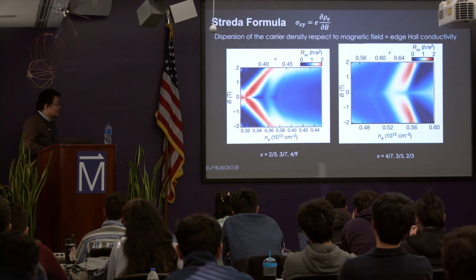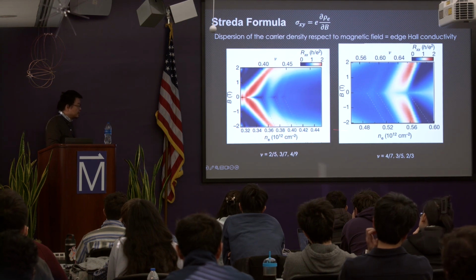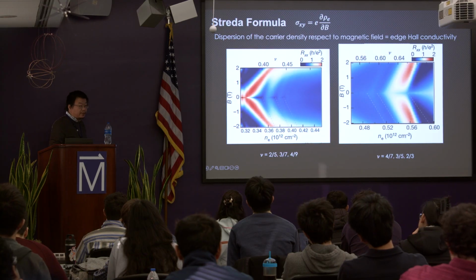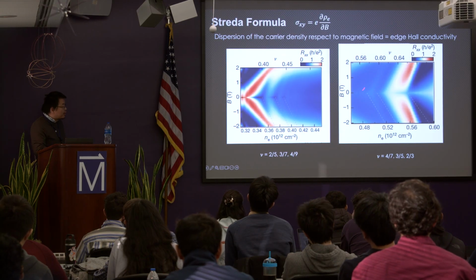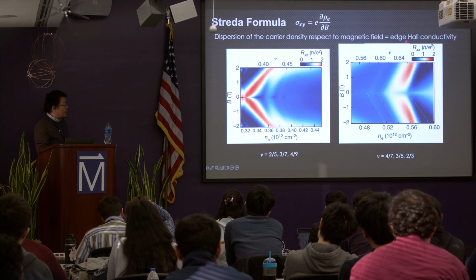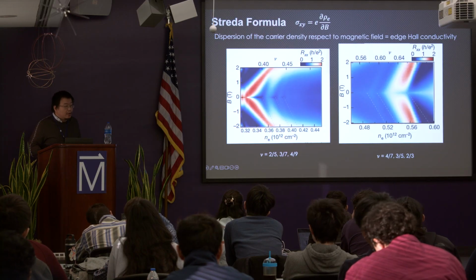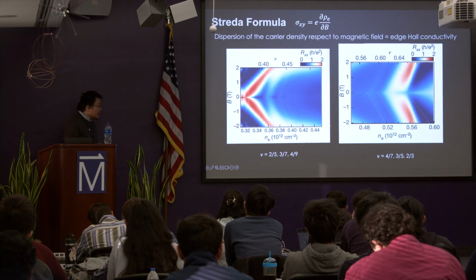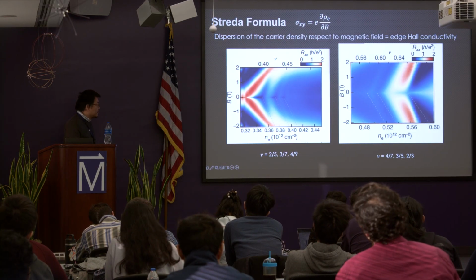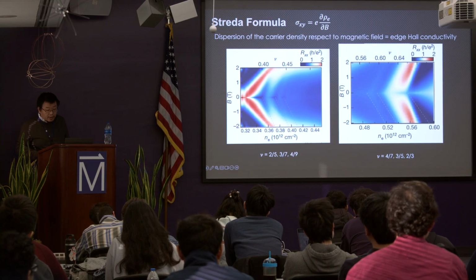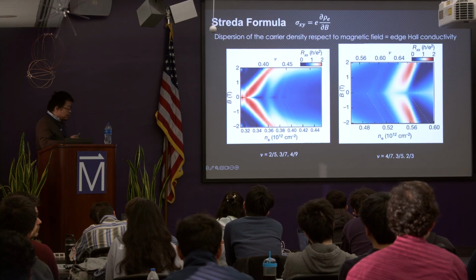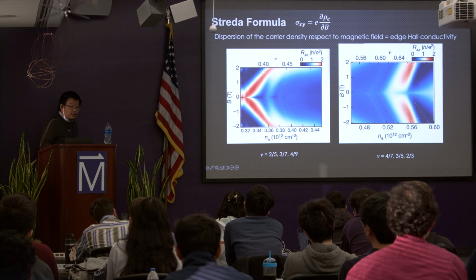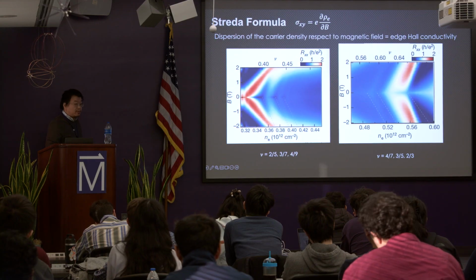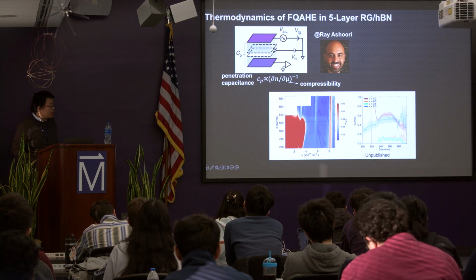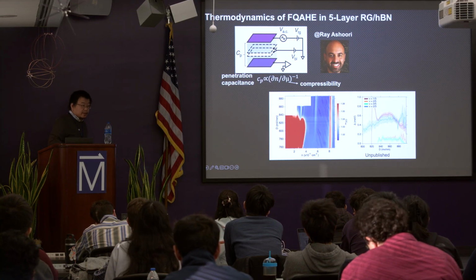When you measure the dispersion of the density versus magnetic field, the slope should match the Hall conductivity. This matches pretty well for all the fractions. You can also cross-check with other experimental methods, for example the compressibility, right? You need to make sure this state indeed stays incompressible.